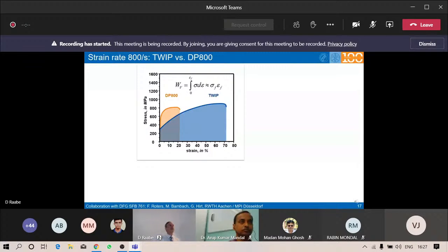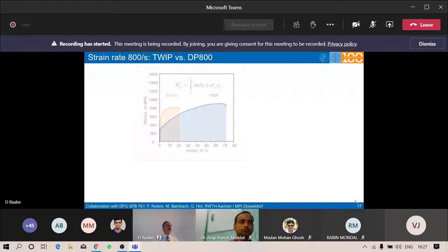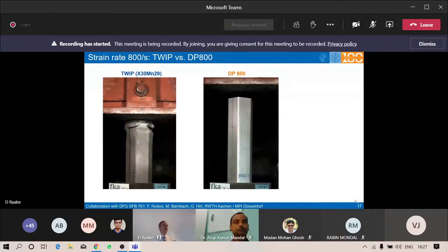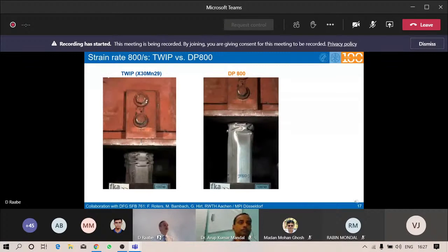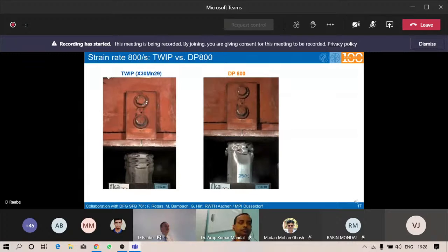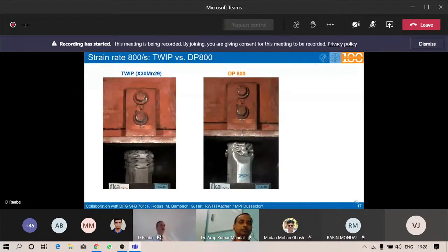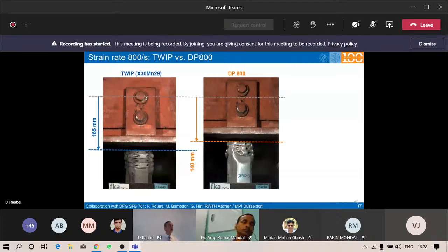And we typically would assume that for a crash relevant forming part, for instance, the TWIP steel should behave quite good because you have a huge integral over stress and strain, which states that a part that is made from such a steel should have a very high energy absorption capability. Now you see here a typical crash experiment conducted on both of these materials with such a typical crash box. And interestingly, we can learn from this that the DP steel with the lower integral, so with a lower total mechanical work, performs actually much better than the TWIP steel with a much higher integral. So that is kind of a surprising result at first view.